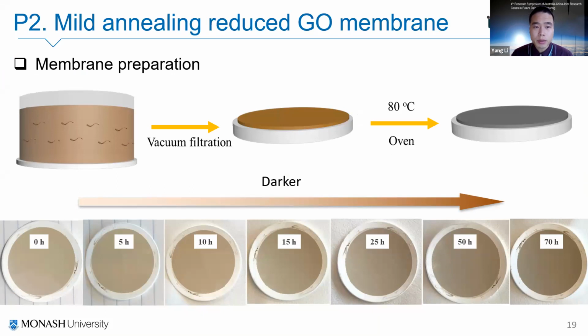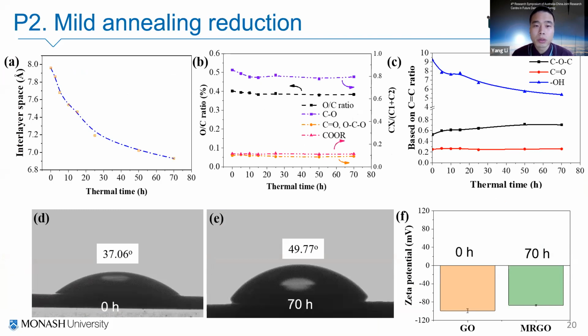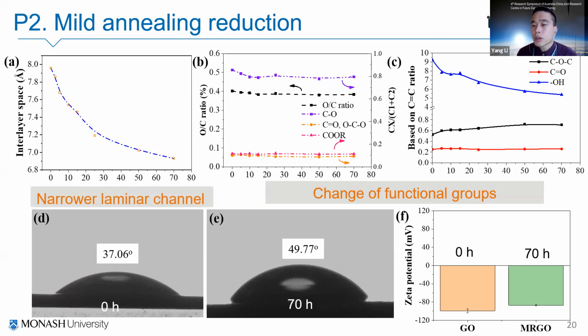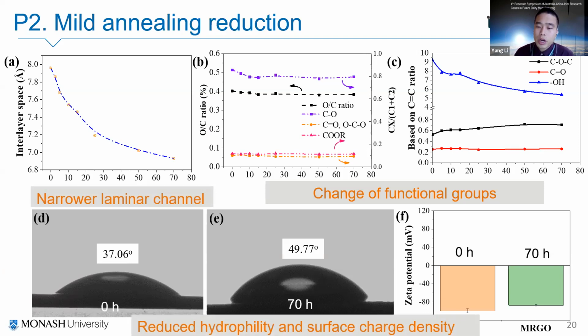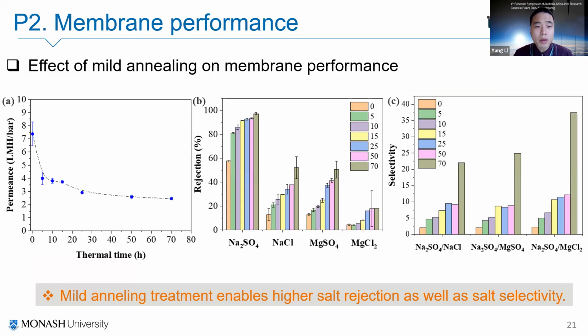Generally, after filtration of the membrane on a porous substrate, we reduce this membrane in the oven. From the superficial view, we can see this membrane after thermal reduction shows a similar trend as the high temperature treatment, in which the surface becomes darker and more black. From some characterizations, we get to know that after the thermal reduction, the channel becomes narrower, and we see the change of functional groups, and the reduced hydrophilicity and surface charge, indicating the mild annealing is able to reduce this membrane. From the membrane performance, we get to know the narrower interlayer spacing leads to a reduced water permeance.